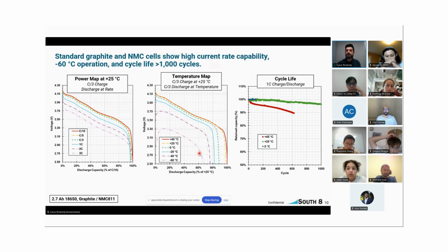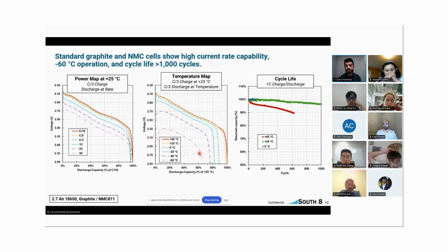Now, as we all know, lithium ion cells with your liquid electrolyte begin to lose performance right around 0 degrees Celsius. By minus 20, you're really losing everything if it's not already frozen. Anything below minus 20, you pretty much lose all your power and capacity in that cell, unless you have some specialty electrolytes, which some people have developed. Here at South 8, low temperature is never a problem for us. We go down to minus 60, still delivering about 70% of your capacity on this specific cell design.